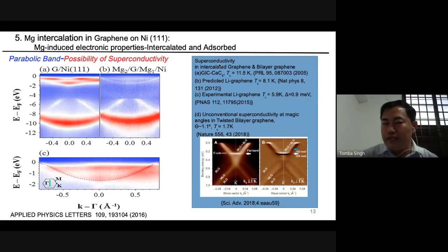As I mentioned in the beginning slides, graphite and graphene don't have superconductivity. But graphite can be induced to superconduct by intercalating metal. For example, in the calcium intercalated case, the superconducting temperature is 11.5 K, so below this it possesses superconductivity. Now the question is, can we induce it in a single layer, a monolayer? It is theoretically predicted, with a transition temperature around 8.1 K. And there is an experimental report of superconductivity observed with a transition temperature of 5.9 K. They explain that this is due to phonon-induced superconductivity.